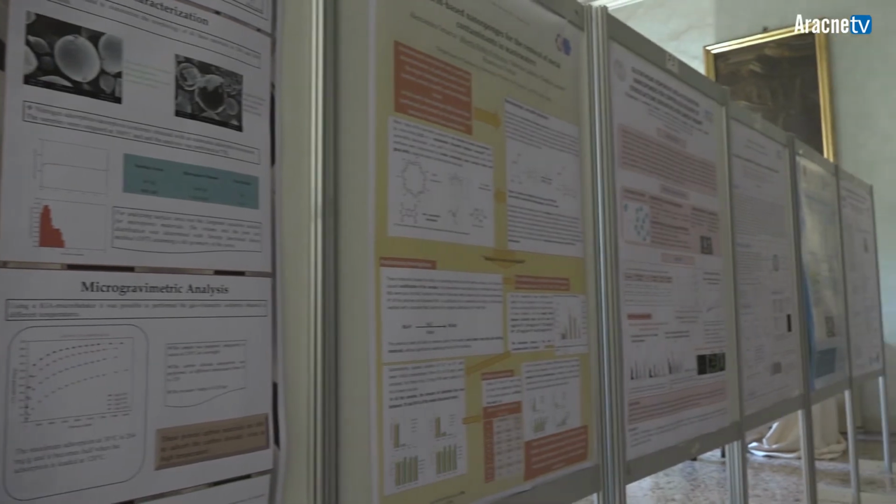My work is basically involved in cyclodextrin nanosponges preparation and application. Cyclodextrins are natural starch derivatives that can form inclusion compounds with a lot of active molecules, in particular drugs, and have actually a lot of applications. Their properties can be improved when a cross-linking reaction is performed, and nanosponges are hyper-cross-linked polymers that show improved performance in comparison with the parent cyclodextrin. In particular, cyclodextrin nanosponges can be used for wastewater removal, as an innovative drug delivery system, as support for enzyme-like catalysis.